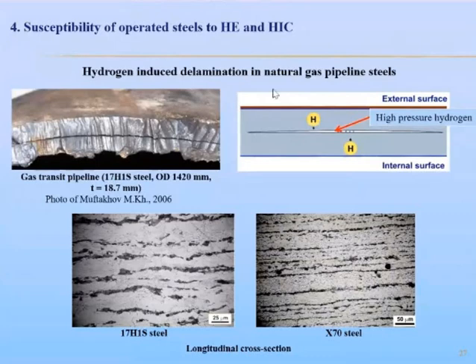And hydrogen charging of a metal from inside of the pipe due to electrochemical corrosion leads to molecular hydrogen accumulation in certain trapping sites, for instance in intergranular defects and the inclusion matrix, and the creation of high pressure in them. Hydrogen being accumulated inside the delamination cavity eventually leads to pipeline damage. As a result of excessive hydrogen pressure, fracture often takes place even in the absence of any external loading.